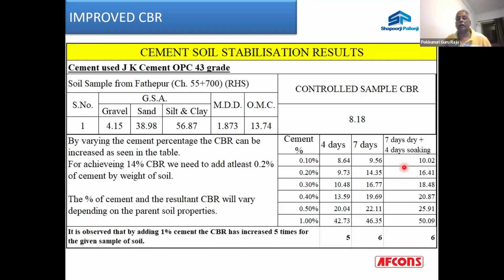Now, there is an important point to be noted. If you are adding 0.2% cement and testing immediately the next day, it's not going to be close to even 8%, because it will be less than what the control sample is. So that is why there is a need to cure the stabilized soil, especially when it is being stabilized using cement. When you are stabilizing with a mechanical method using materials other than cementitious ones, this is not going to be that critical. But when you are adding cement, curing plays a vital role and it adds value to your strength, thereby optimizing the doses.